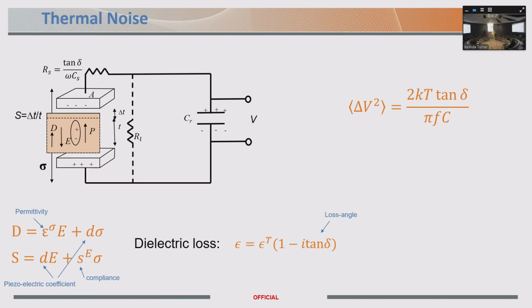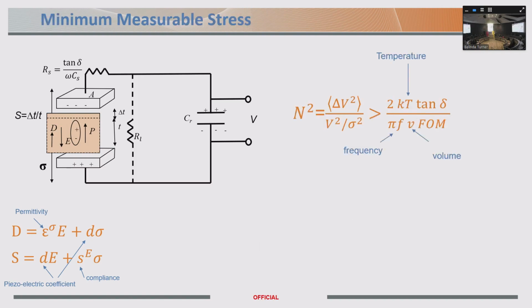It's actually the minimum energy. You can see that's proportional to V squared. So it's actually the minimum energy that can be measured. And when you take that minimum energy that can be measured and divide it by the energy per unit stress that you can achieve, what you get is effectively a measure of your noise floor or your sensitivity. And that's what we call sensitivity. So that is the minimum amount of stress that can be extracted by that material per unit volume, per unit field.